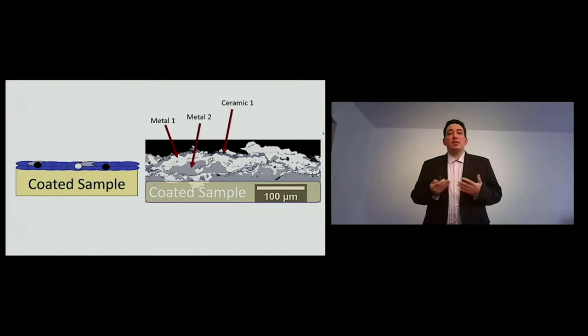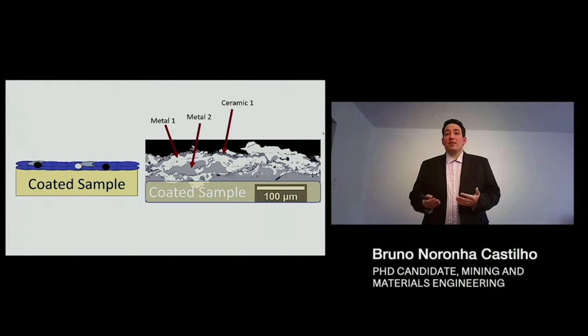However, we noticed that we didn't find the ceramic two that was supposed to be there. Furthermore, the coating had really bad properties like mechanical strength, adhesion, and cohesion between the particles. The last problem that we have is that the coating is really thin, indicating a really bad deposition efficiency. So based on the lack of the second ceramic, because that one is the one that has the highest melting point, we thought that maybe what happened is that the stream was not hot enough to melt all the particles.